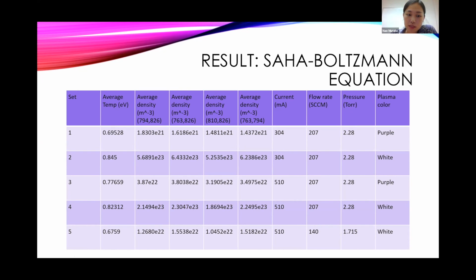And also similar to the temperature, white plasma has higher density than purple plasma. Then we compare set 2 and set 1. Set 2 has higher density than set 1. And when we compare set 4 and set 3, we see set 4 has higher density than set 3.